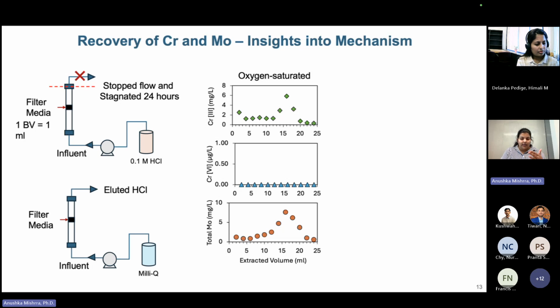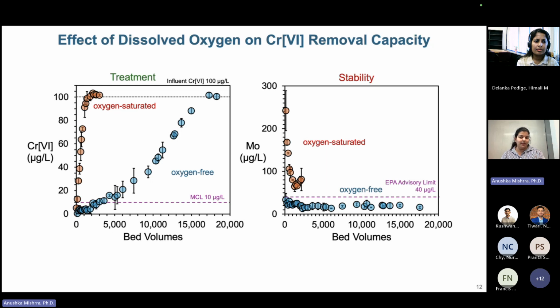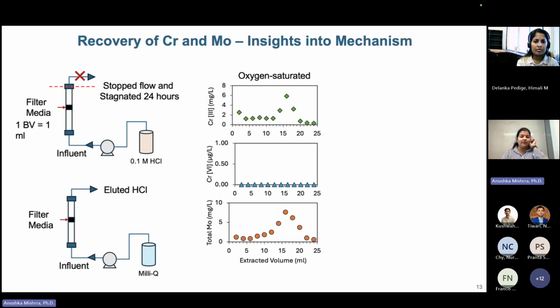Part of the intention of this work is to show that it can be used as a viable treatment technology. We wanted to see that after running the treatment, since we still had a lot of material left, how we could reuse it. One way to reuse the material is to simply clean it, and we tried a lot of different methods to do so. The most effective method was washing the filter with hydrochloric acid.